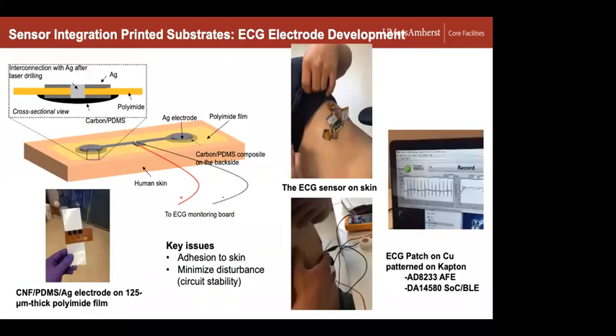Here are some examples of how we actually develop materials and designs to specifically integrate the electrodes. This is an example of a topside printed circuit made of silver, like I've just shown you in several examples. On the backside, we integrate a carbon electrode, a specific material that one of the Watkins postdocs was looking at. We're able to pattern that, print the electrode configuration, and then wear that and do some example testing in a body-worn situation.